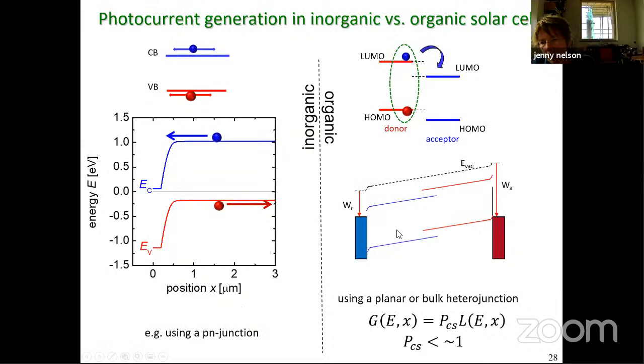Now in this diagram, I create the exciton, it's able to diffuse, and then it breaks. It breaks because the exciton reaches a point where it is adjacent to another molecule or another domain with a different chemical structure. It's more attractive for electrons. It has a deeper lying LUMO, so higher electron affinity, and the electron would rather be there. So it's presented with the opportunity of, rather than the exciton moving to another molecule, the exciton breaking and the electron transferring, which would be energetically favorable.